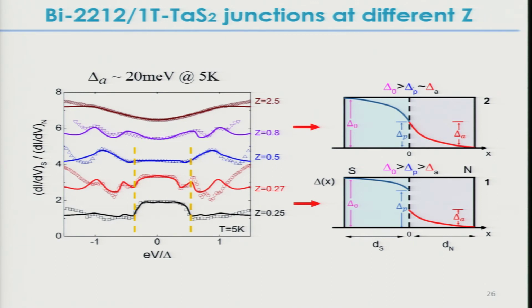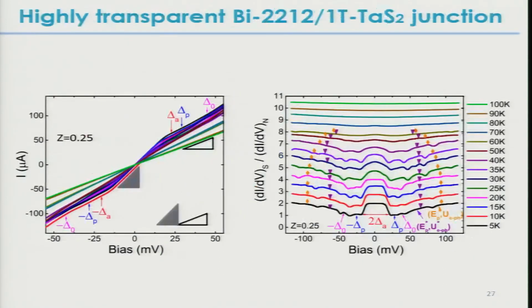So we've induced high TC in this Mott insulating phase. And the CDW doesn't destroy it. If anything, it's coexisting with it. Whether it helps it or not, we don't know. So this is an example of inducing high TC superconductivity in a Mott insulating CDW phase.